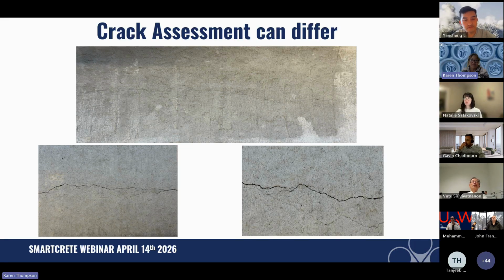The other thing is crack assessment can differ. Crack assessment varies by the operator and what the operator sees, the camera that's utilised, the equipment, the distance the camera ends up being from the wall of the pipe, the level of zoom that's applied with the camera, and even the cleaning. The spec says they have to clean the pipeline, and they clean it through pressure cleaning, so the walls are very, very wet, and every little hairline crack looks like a canyon. You can see from these pictures, this is just the same image with 3 different zooms. If you saw the top image, you'd go, maybe there's a very, very small hairline crack. When you get to the zoom on the bottom right, that is disaster, and it would be pulled out. But the reality is the pipe has a very acceptable crack width. And that's just one of the issues we get from the CCTV reports.